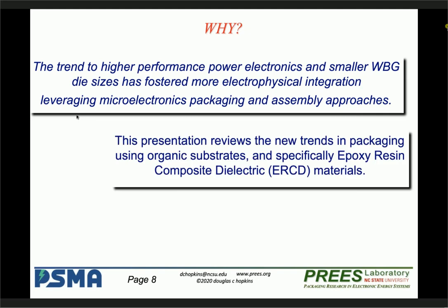And what we're focusing on, again, I mentioned that there are other organics we're typically using in printed circuit boards, et cetera, the polyimides, et cetera. But instead, we're focusing very heavily on these epoxy resin composites. And what the composite is that these companies are taking epoxy resins and infusing them with aluminum nitride and aluminum oxide, alumina powder. And so therefore, they're getting the thermal conductivities up while still maintaining the benefits of epoxies.